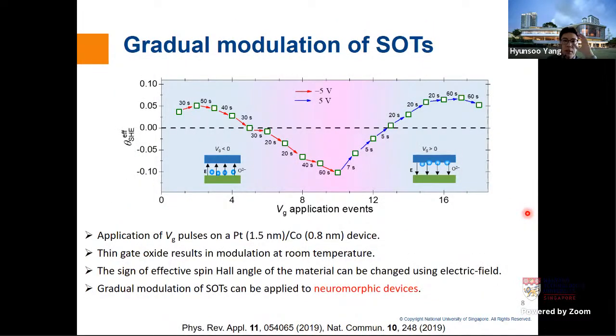But we also find very interesting behavior depending on the programming time in this device. So we apply negative voltage, then eventually this should go to an effectively negative spin Hall angle because of oxygen accumulation in the cobalt layer. But depending on how much we apply, so we apply 30 seconds, 60 seconds, additional 40 seconds and so on, and applying very, very slowly, we found there is a gradual change of the status of this device. And then from the effectively negative point, now we can apply positive voltage, and then you can see it will bring it back to the positive state in a very gradual fashion. So this indicates we can think about some kind of analog-like application, which is neuromorphic devices.